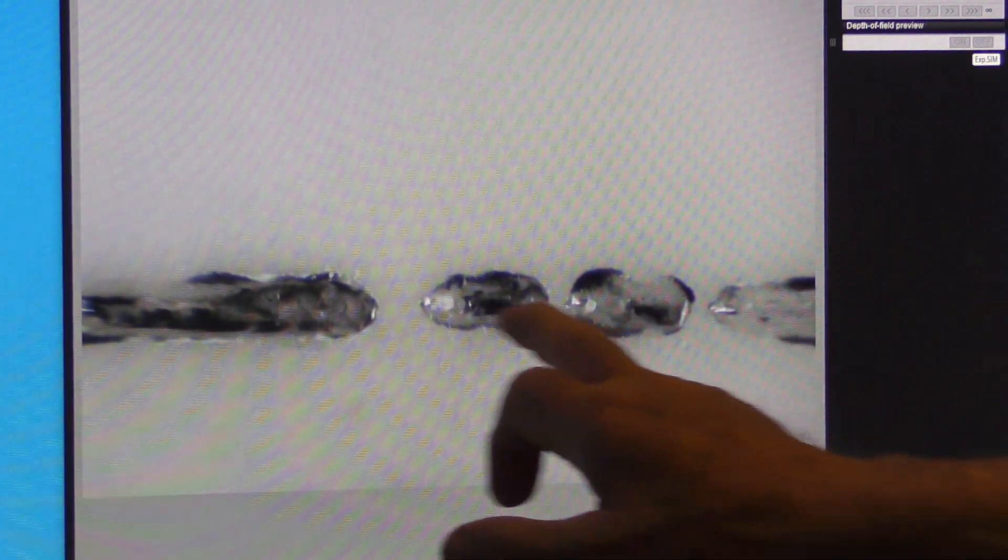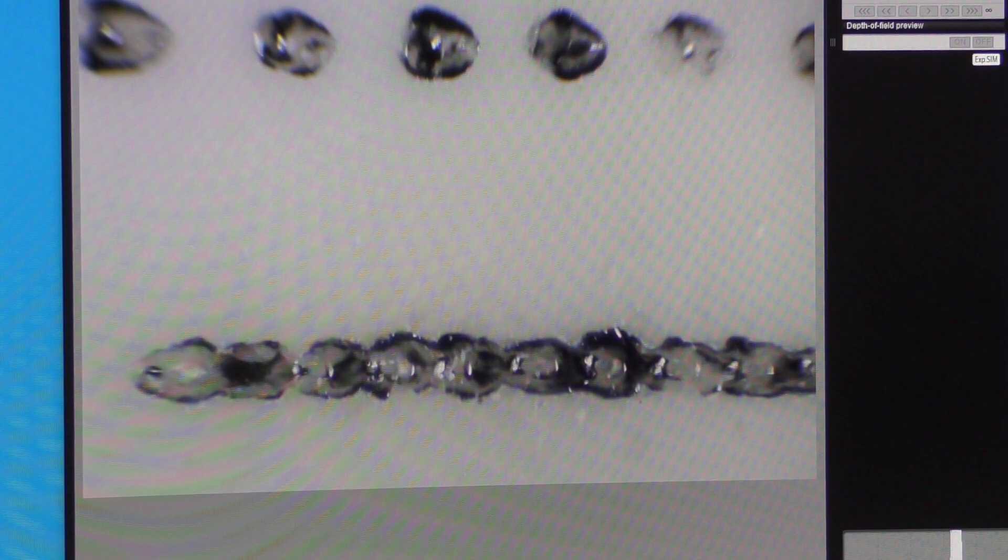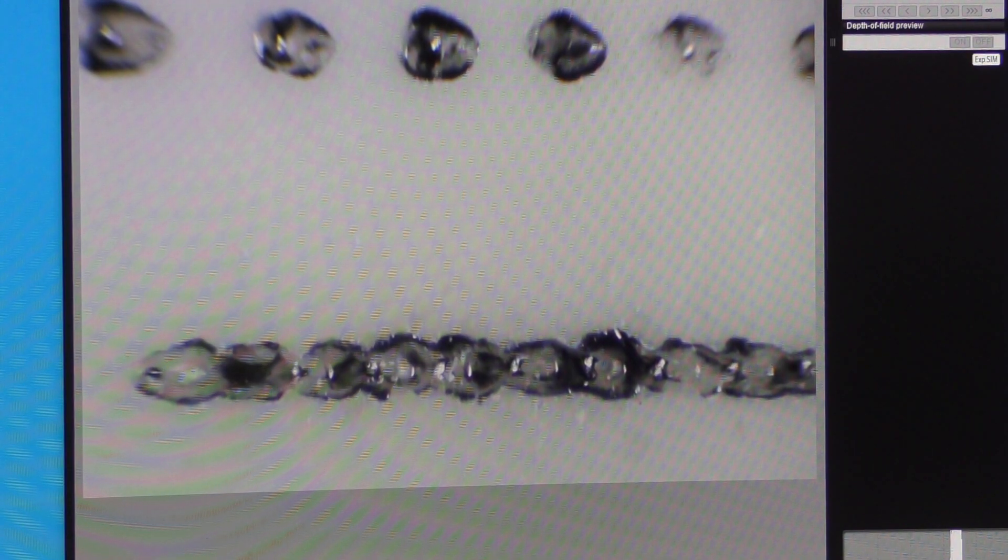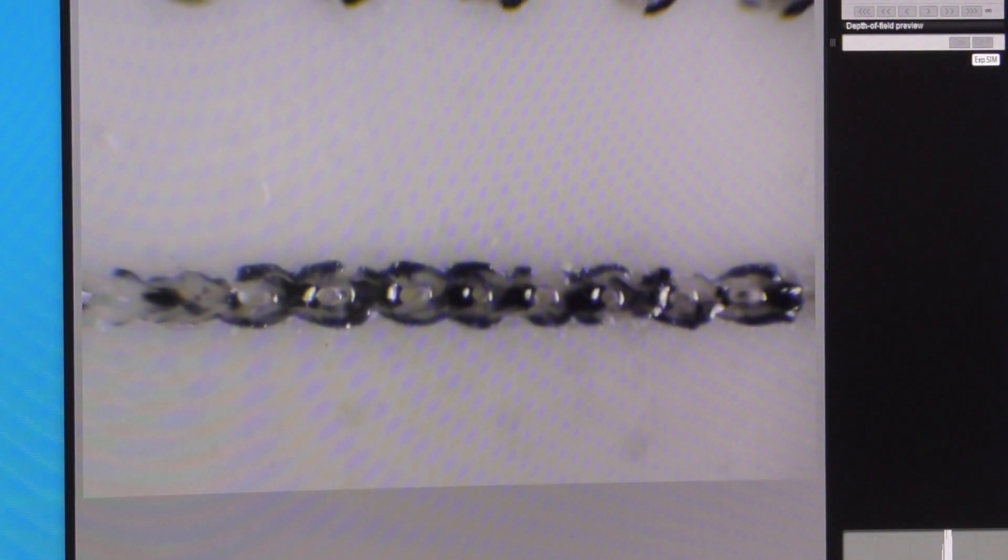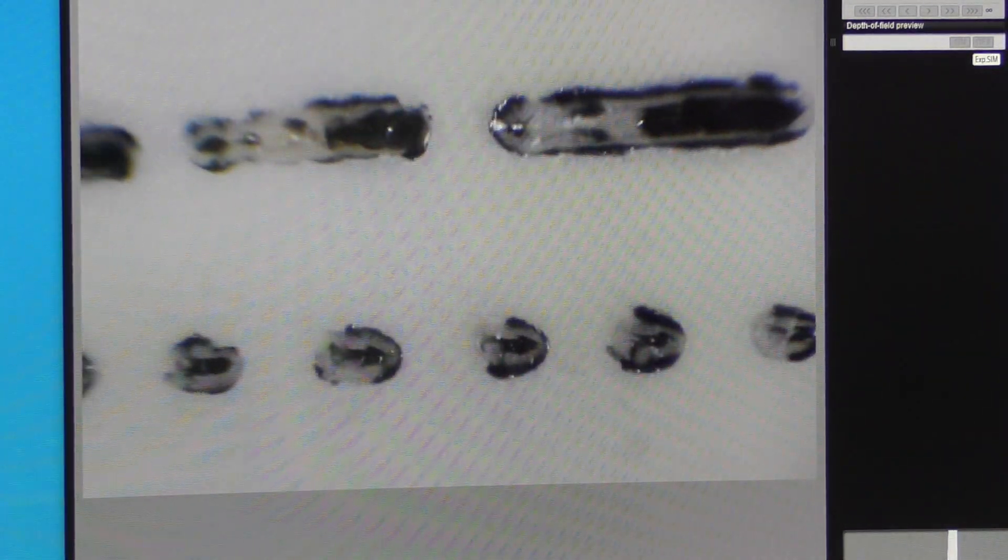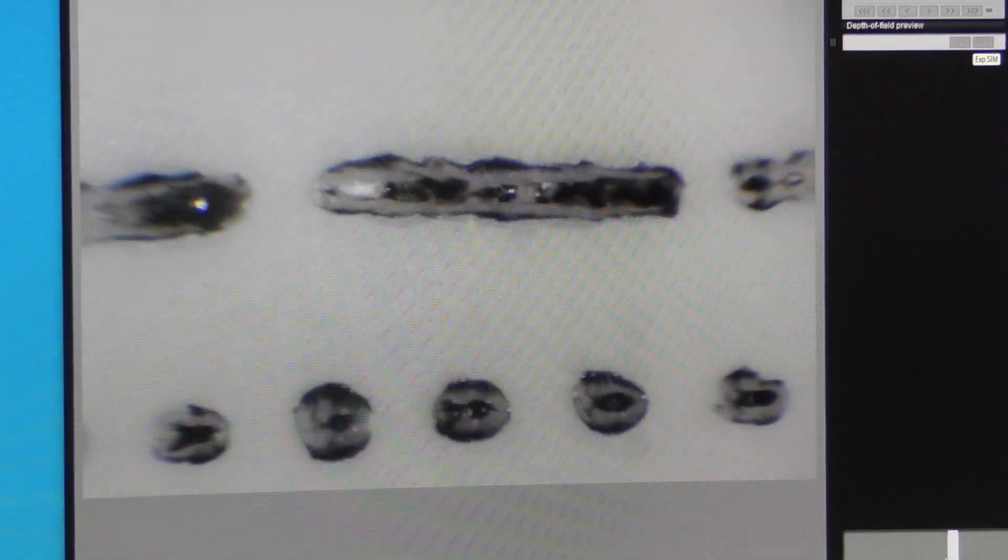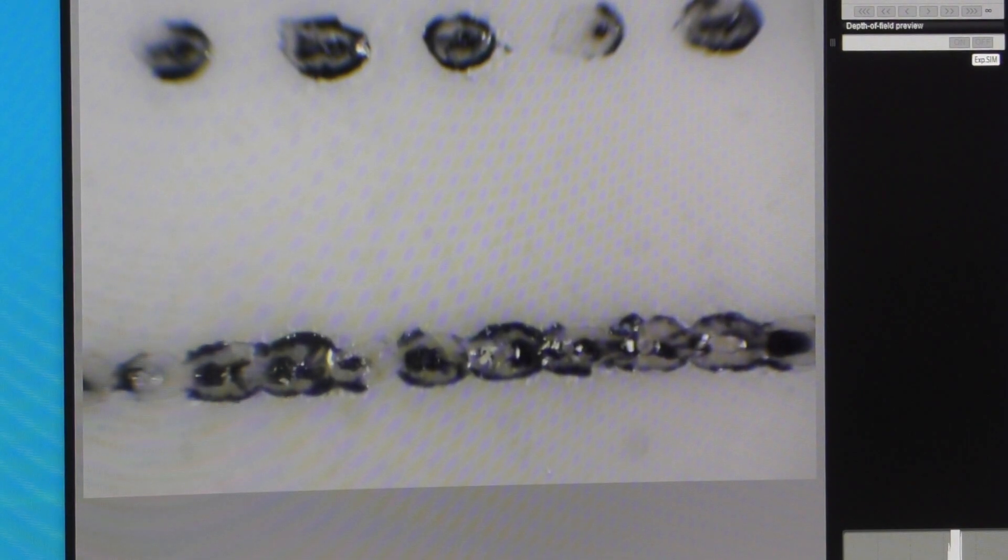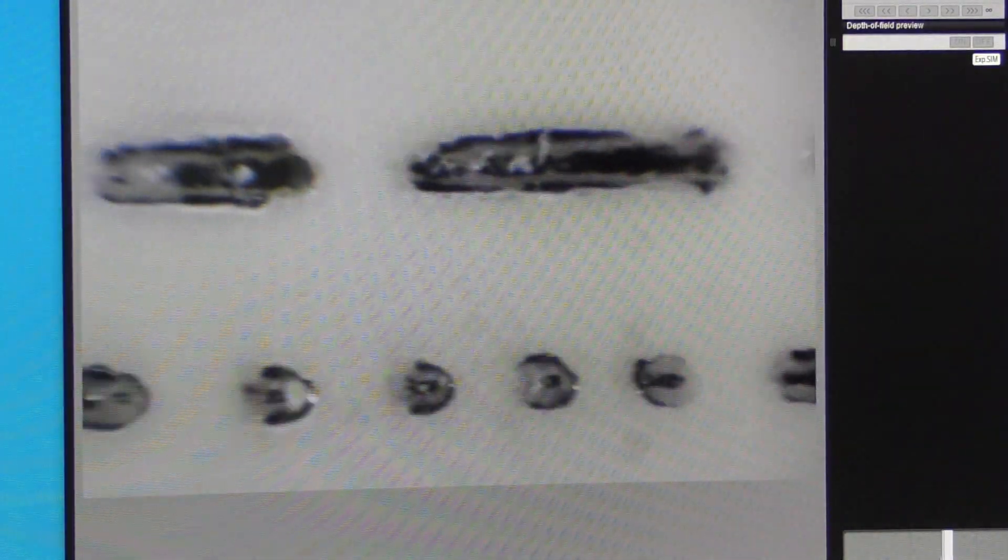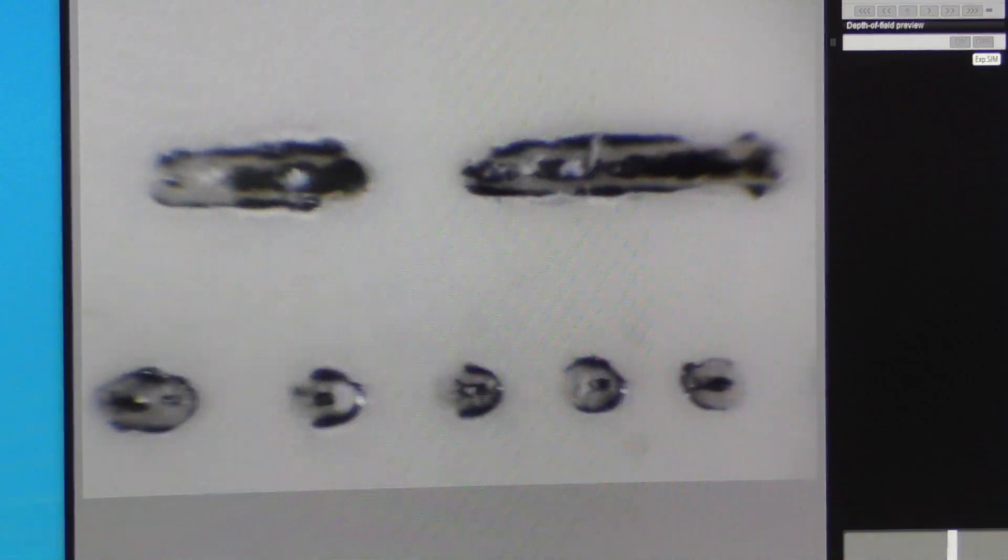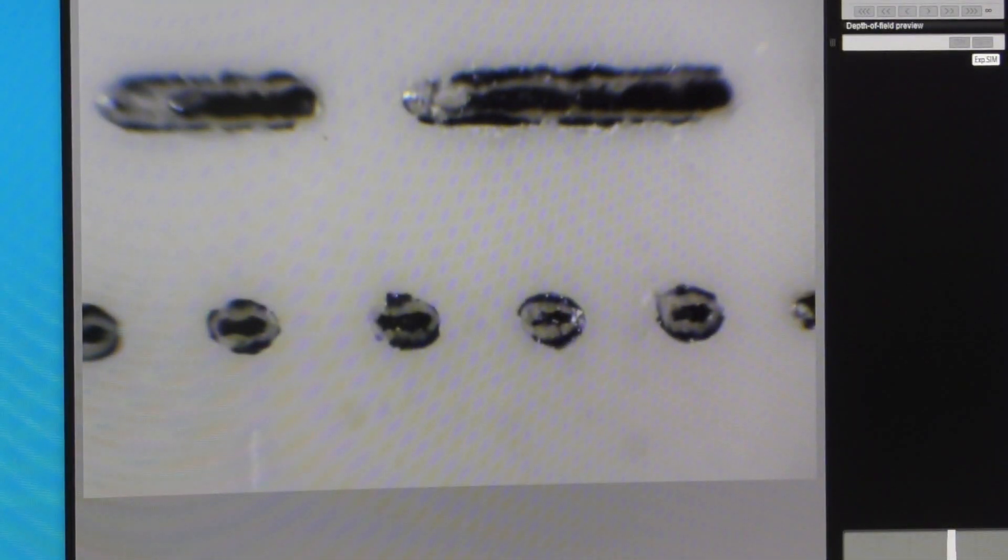Starting right at the top there. 200mm a second. 50% power. With that much power, we look as though we're burning into the glaze quite a lot. And, we're not actually making much impression with color. That may well be due to the paint brush effect where I wasn't getting the titanium oxide on in a nice uniform layer. Alright. So, that may account for some of these little problems here where we haven't got any color. Where we do have color, it's not all that distinct, is it? So, we'll drop it to 40% and see what happens. Well, we're getting some distinct color now down the centre of those dashes. And, it still looks a bit like Frogspawn. So, let's drop it down to 30% power. Hmm. It's getting better. We've got a more uniform sort of pattern now. 20% power.